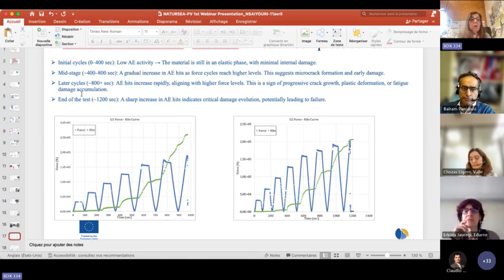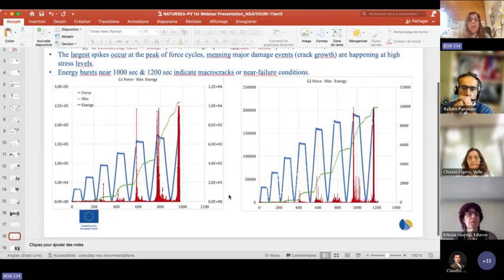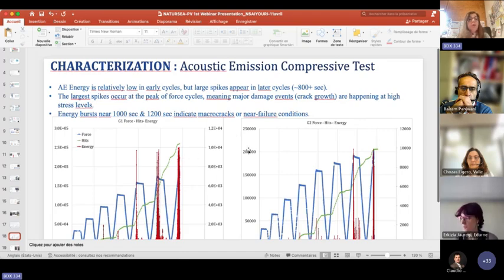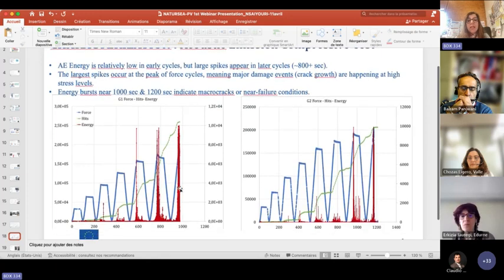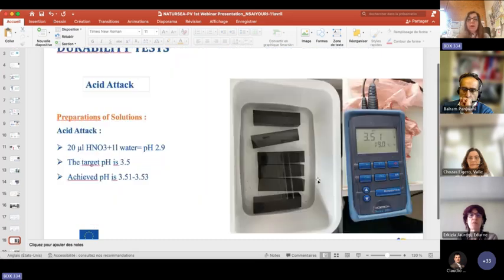Or you can also talk about damage accumulation and fatigue accumulation with these tests or cyclic tests. And at the end, we have a sharp increase, what we see here, and we have the damage evolution or failure, in fact, of the specimen. We can see the same thing with the energy, which gives the same indications. The spikes occur at the peak of force cycles. If you see those red peaks, they show crack growth in the sample at high stress level.